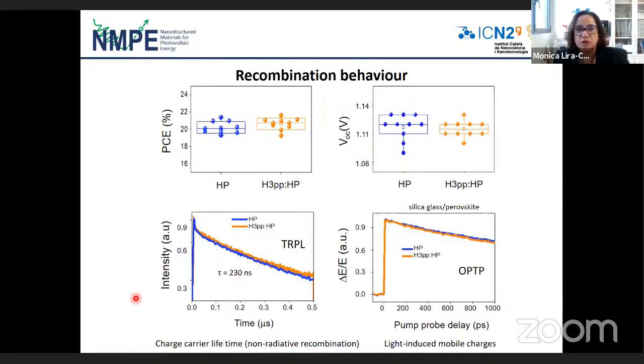So here you can see that charge carrier lifetime related to non-radiative recombination and the density of defects were very similar both with and without the additive.